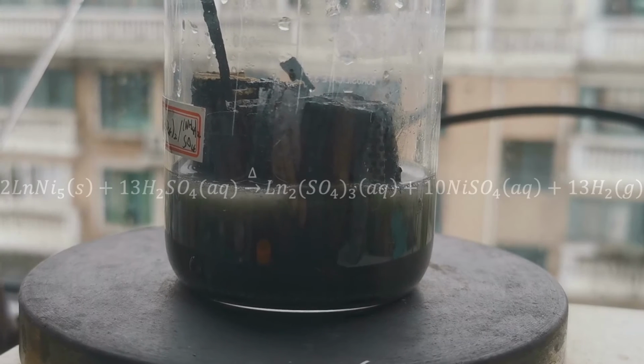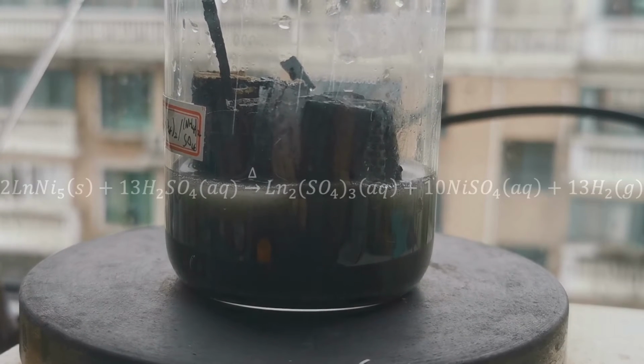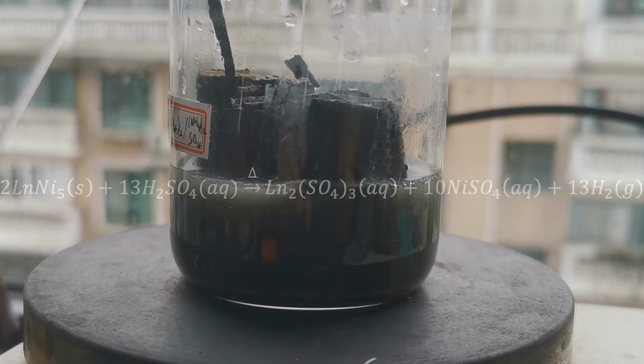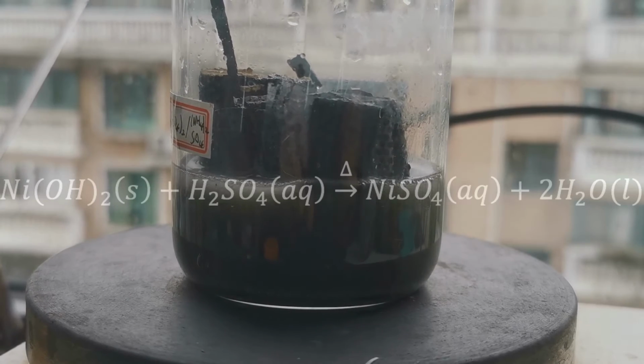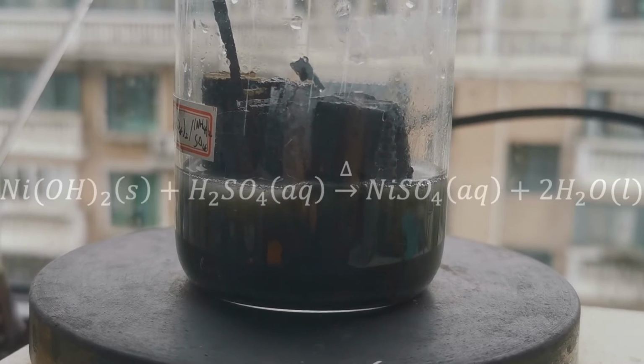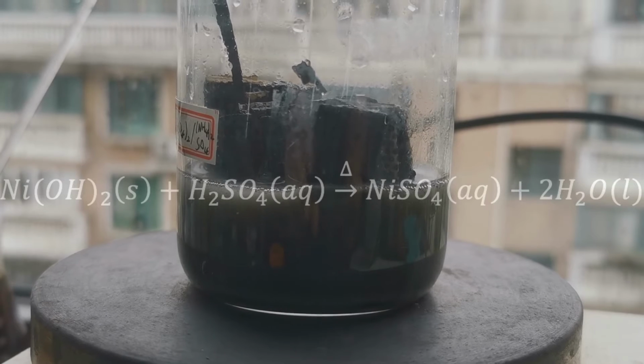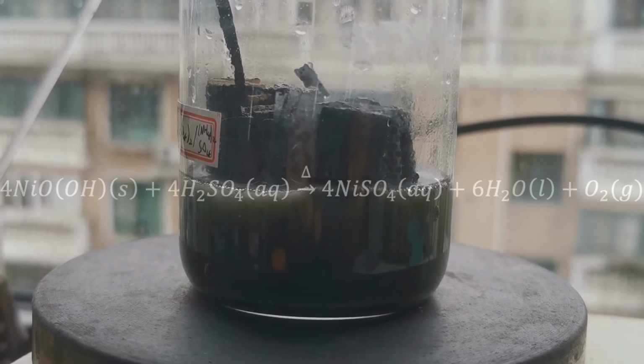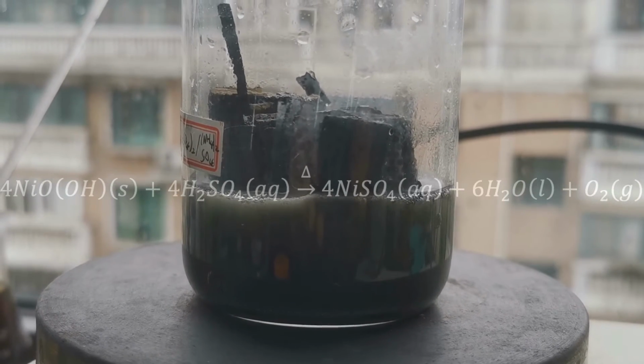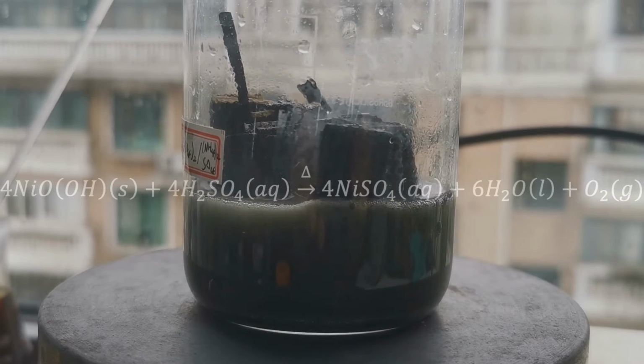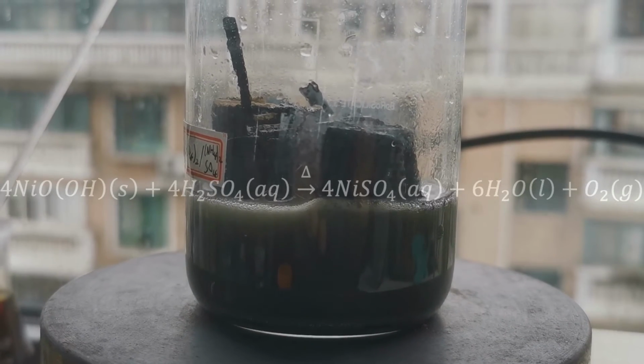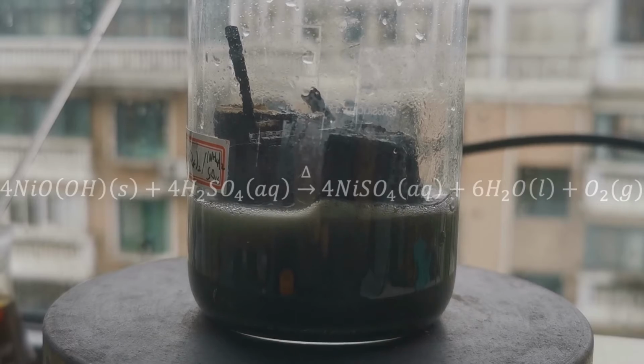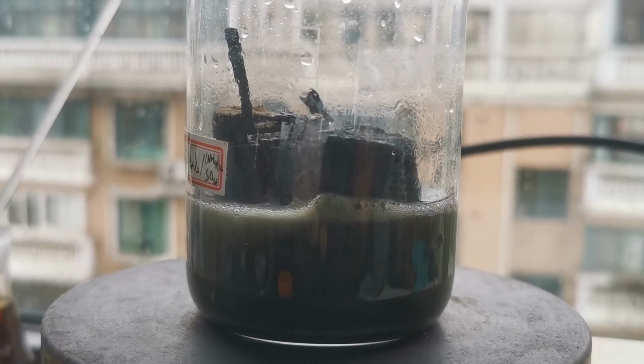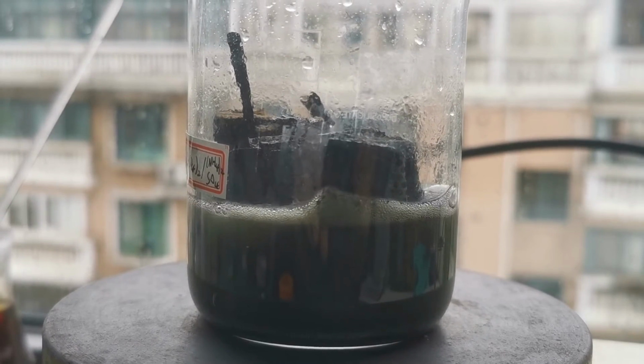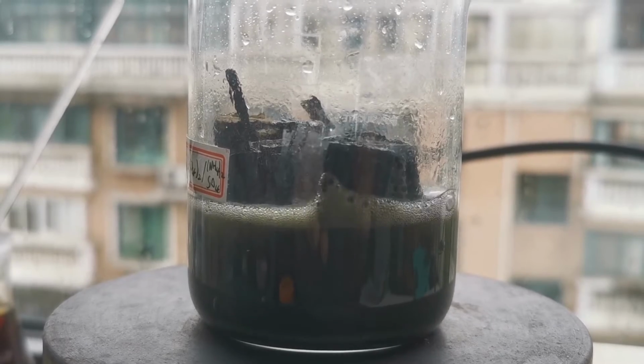The nickel lanthanide alloy is reacting with sulfuric acid to produce nickel sulfate, lanthanide sulfates, and hydrogen. The nickel hydroxide also reacts with the sulfuric acid to give nickel sulfate. The battery may also contain some nickel hydroxide oxide from incomplete discharge, which also dissolves in sulfuric acid, but it releases oxygen instead of hydrogen. Finally, the metal mesh is made of stainless steel, which dissolves in acid to produce ferrous sulfate, nickel sulfate, and